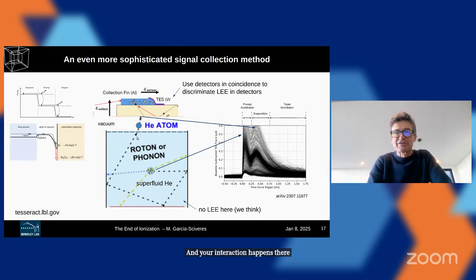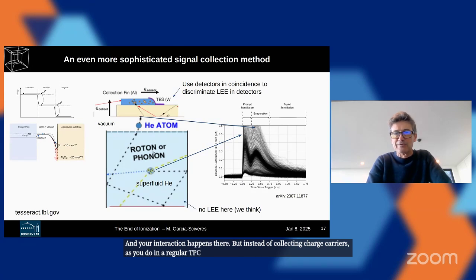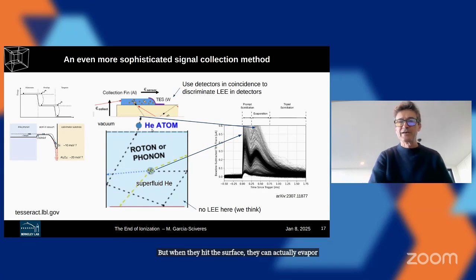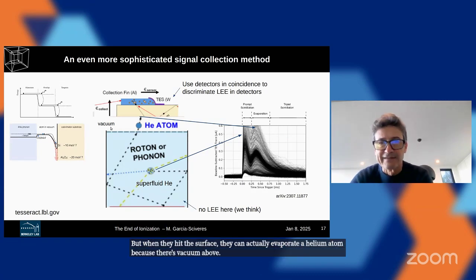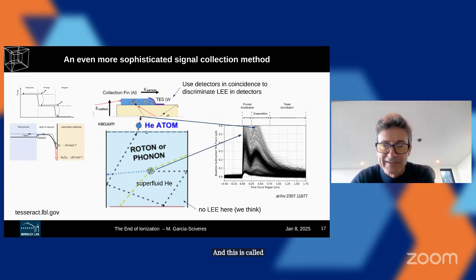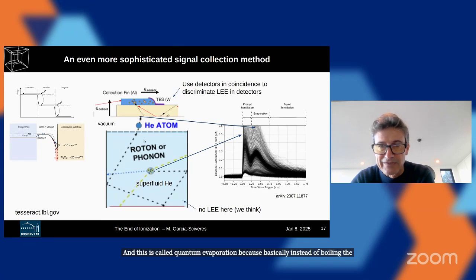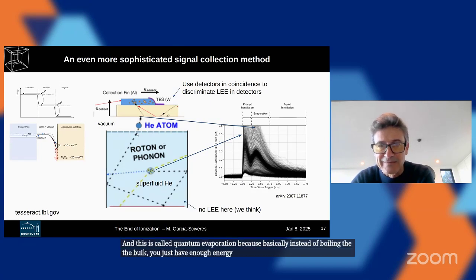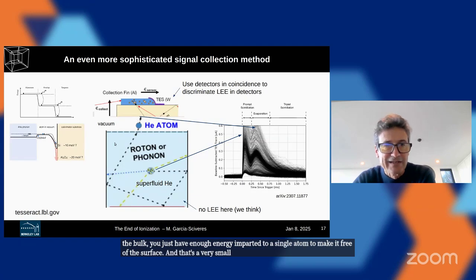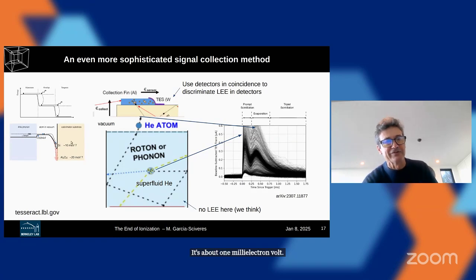But instead of collecting charge carriers, as you do in a regular TPC, now you have phonons and rotons, and they don't drift like in a regular TPC, they just bounce around. But when they hit the surface, they can actually evaporate a helium atom because there's vacuum above. And this is called quantum evaporation because basically instead of boiling the bulk, you just have enough energy imparted to a single atom to make it free of the surface. And that's a very small amount of energy in superfluid helium. It's about 1 millielectron volt is enough to evaporate an atom.